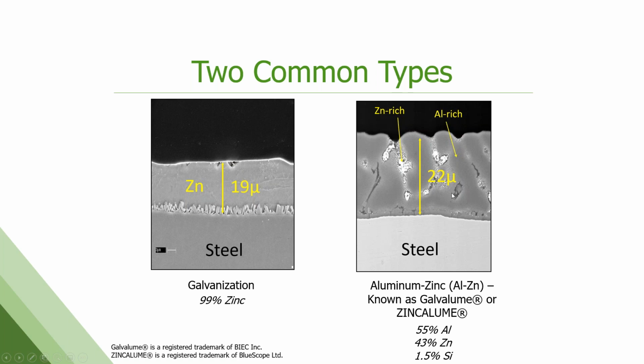The white parts in this picture are the zinc rich areas. The gray is the aluminum. So you can see by volume that there's much more aluminum going on here than there is zinc. What happens is these little zinc areas will sacrifice themselves and corrode on exposure, but this aluminum stays in place. So while you get some voids once this zinc has been sacrificed, you still have all this aluminum left on the surface doing its job.